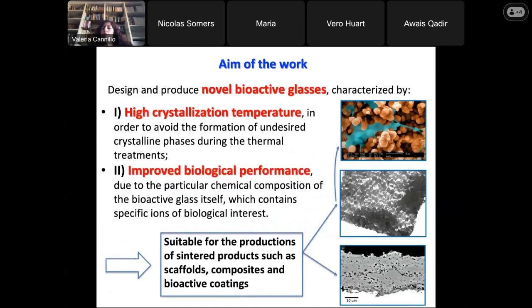This is the reason why in our group we have designed and produced novel bioactive glasses. Such glasses are characterized at the same time by very high crystallization temperatures and improved biological performance. The high crystallization temperature is designed in order to avoid the formation of undesired crystalline phases during the thermal treatments. And at the same time, adding to the glass composition the so-called therapeutic ions, it is possible also to improve the biological performance with respect to the 45S5 original composition.